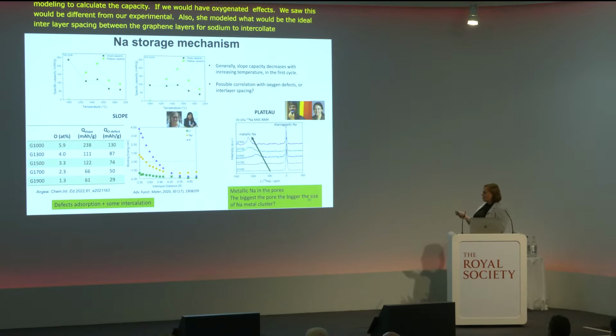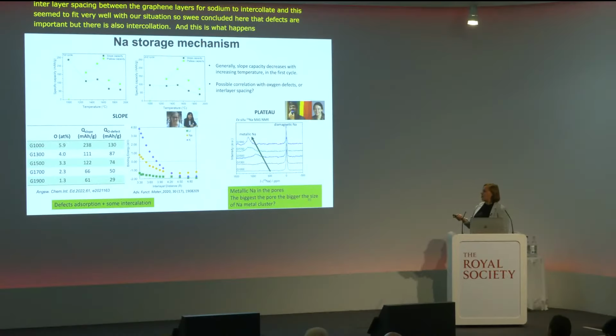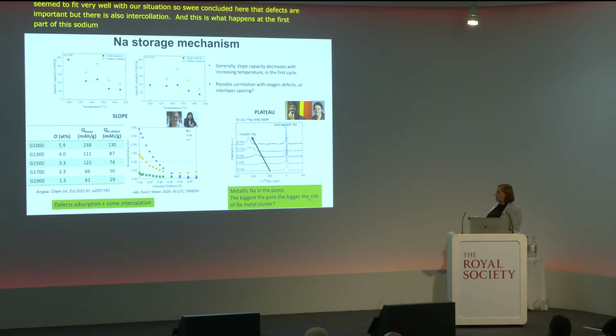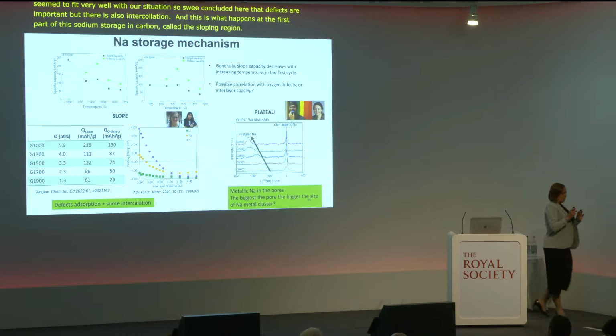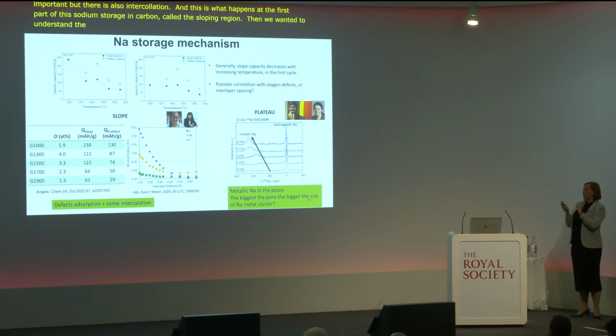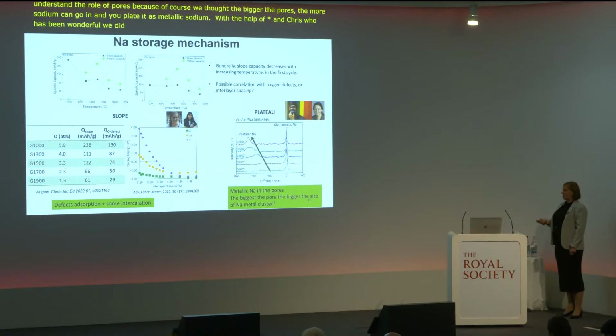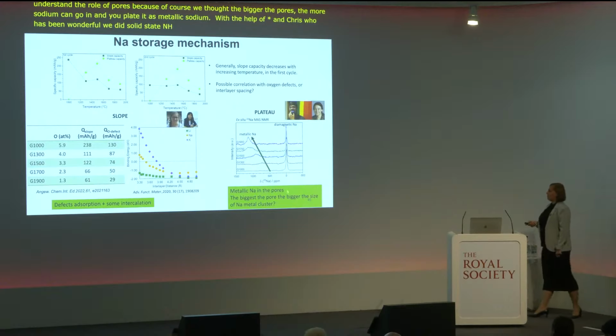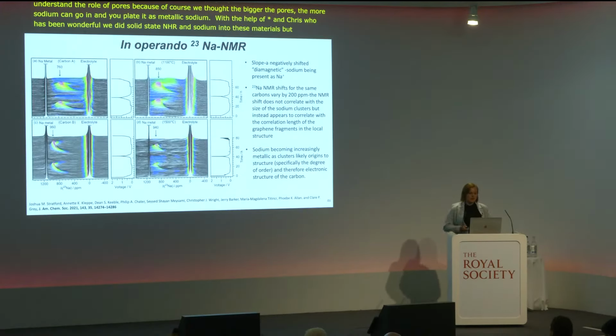So we've concluded here that defects are important, but there is also some intercalation. This is what happens at the first part of the sodium storage in carbon, which is called the sloping region. Then we wanted to understand the role of pores, because of course we thought the bigger pores we have, the more sodium can go in, and you plate it as metallic sodium. So with the help of Clare Grey and Chris, who's been wonderful, we did some solid-state NMR, and we've seen a peak for metallic sodium in these materials, but it seemed not to correlate really with the pore size, so we were wondering what's happening.